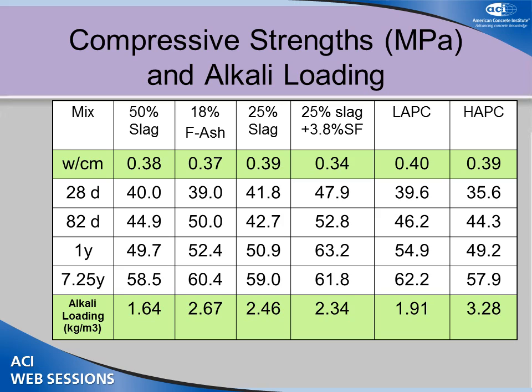The strengths at 28 days. There's the water cement ratios. We were targeting about 0.4 or just under 0.4 to meet the highway maximum limits. But the ternary blend with silica fume had less because we used a high range water reducer because of the silica fume. So it was somewhat lower water cement ratio. The 28-day strengths were in the order of about 40 megapascal, which I think is 6,000 psi. And you can see that at 7 years they're up around 60 megapascals generally.